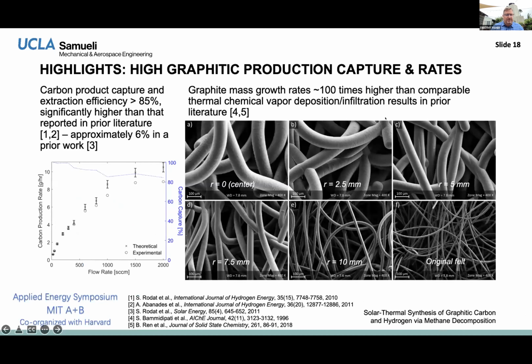So I mentioned before that we can look at this and we have this big temperature gradient. If we look at the center, this is what the center looks like at the end of the process. This is what the original felt looked like, and these are all at the same scale. There's a very, very strong rapid growth rate at the center, but it drops off in about 10 millimeters of radius. So you could think of about an inch and a half diameter as the sweet spot. And we've also varied things like flow rate.